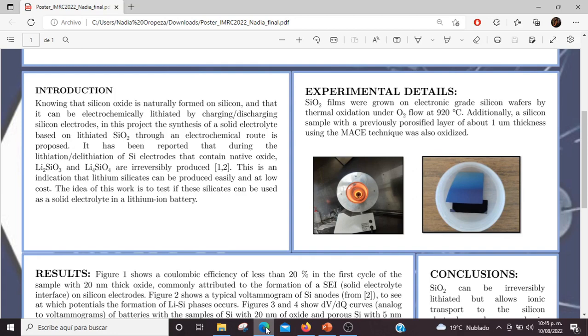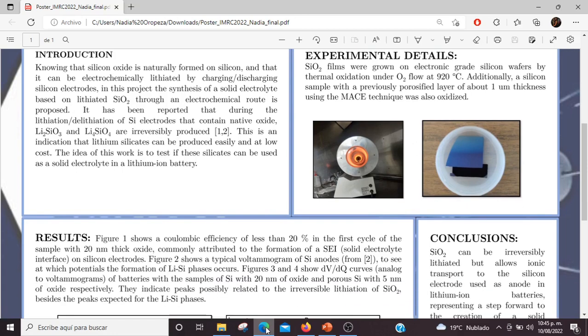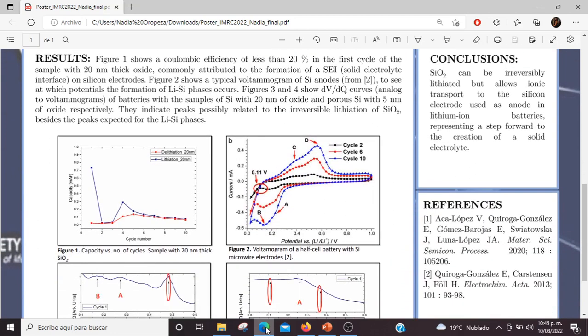The different oxidized silicon samples were assembled as electrodes in battery half cells with lithium as counter-electrode and LP30 as liquid electrolyte. The cells were subsequently subject to charge-discharge cycles. From the curves of storage capacity against the number of cycles, a Coulombic efficiency of less than 20% was observed in the first cycle in all the samples. As an example, figure 1 shows the case of the sample with 20 nanometers oxide.